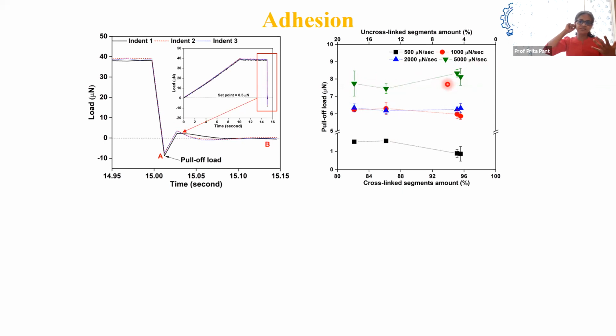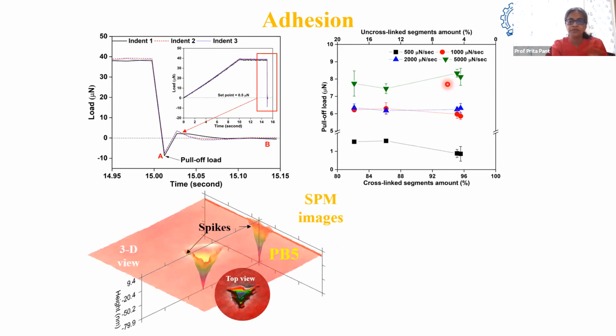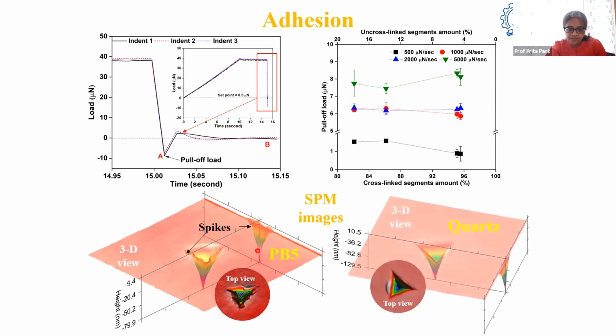Okay, but we said, okay, there is adhesion. Maybe it can complicate things, especially when we are loading the sample, because then we are literally pushing the two surfaces together. So we did decide to gold coat the samples to get rid of adhesion effects, a very thin layer, just enough to get rid of it. And here is a pictorial view of what adhesion does, right? So this is an SPM image of the indent, and you can see these spikes. I think there's a better figure in the next slide, but you look at this surface, which is in SU8, the PBS sample, and look at this in quartz. It's so smooth after unloading, right? So we believe that all of these jagged edges that we are seeing is because of pulling off the tip from a surface which is sticking to it, and that could complicate your results.